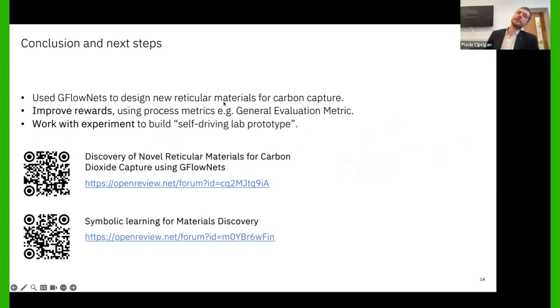So finally, I will conclude and we can talk a little bit about some of the next steps. So here, we've managed to use GFlowNets to design new reticular materials for carbon capture. They are novel, they have high performance. And in the future, I'd like to continue building on this to improve the rewards. So as you can see, for example, the CO2 and N2 selectivity isn't that good. So we'd like to use some process metrics. For example, there's a thing called the general evaluation metric, which shows how good this material is at capturing CO2 in an actual power plant, and move as quickly as possible to work with some experimentalists to build a sort of prototype of a self-driving lab. So where GFlowNet suggests some materials, and they are tested in the laboratory, and we aim to optimize and sample for a proxy of the actual lab measurement.